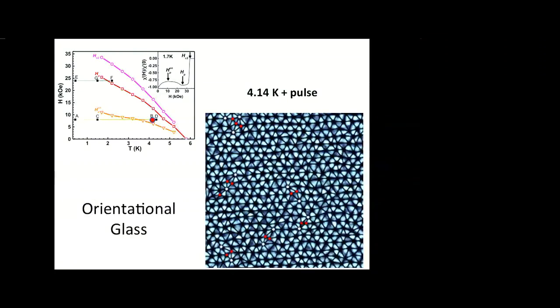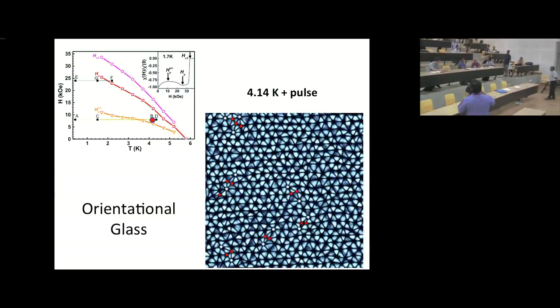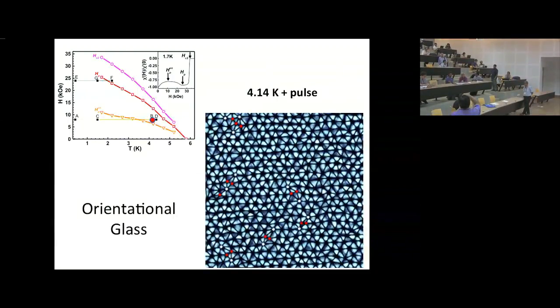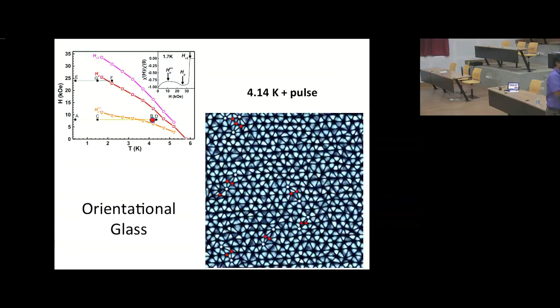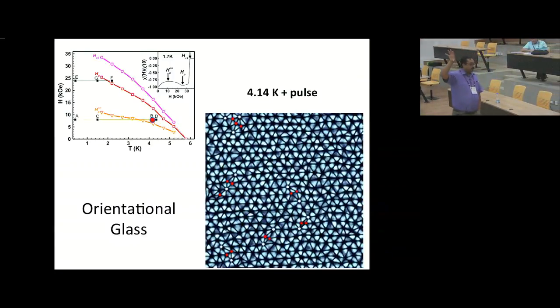Direction of the flux: what we are measuring is not the flux, because what we are measuring is actually where there is a vortex core. So no, I cannot measure the direction of the flux. That is one of the major problems in this vortex lattice physics. You have magnetic field probes, like for example scanning SQUID, but magnetic field probes don't have the spatial resolution at all close to this, because here the magnetic field contrast is tiny. The penetration depth is much larger than the coherence length, so the magnetic field variation can be of the order of a couple of percent, which no probe can actually pick up at the moment. But what we are looking at is the spectroscopy of the core. That is why we are able to see isolated vortices, because that's much better resolved.